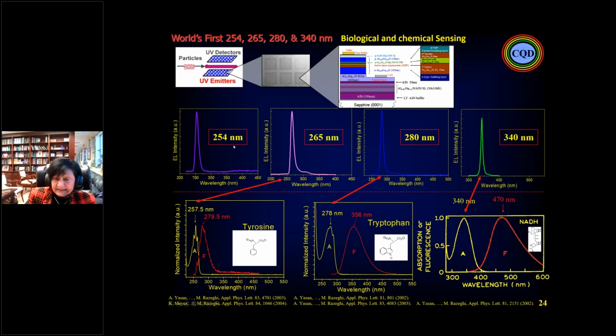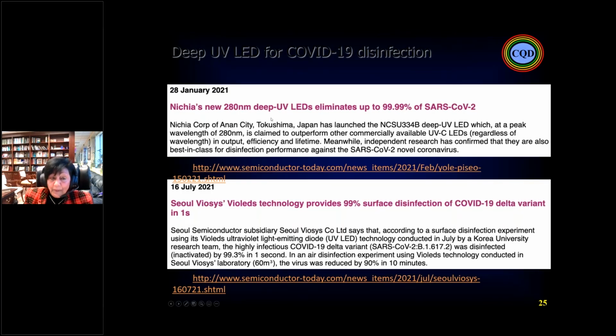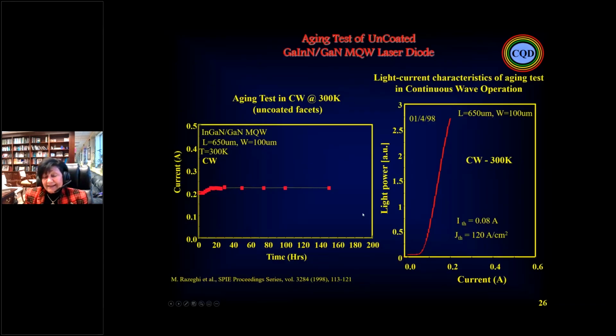So last year, just recently, we are doing gallium oxide, which is, again, a wide band gap. And the question was, what is important? I explained that for the coronavirus, it is important to study this material at the present time. Of course, many could not really understand, but immediately the Japanese and Koreans used 280 nanometer deep UV LED to eliminate up to 99.99% of SARS-CoV-2. And in Seoul, they tried to show that by using UV LED, they can provide 99% surface disinfection of COVID-19. So you can see how important this material is.